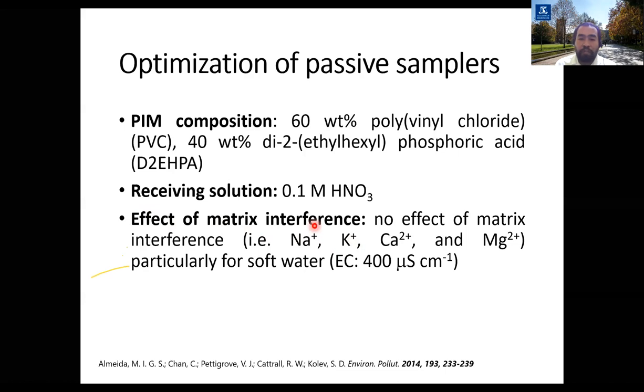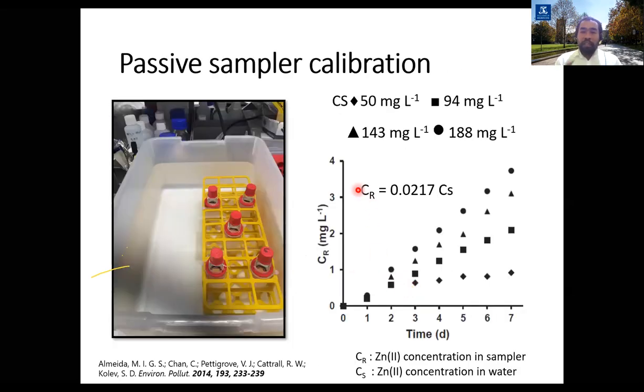They have also studied the effect of matrix interference, where they found no effect. It is commonly found in environmental water that sodium, potassium, calcium, and magnesium are the most commonly encountered cations. And because the mechanism of the accumulation of zinc is cationic exchange, these cations are expected to interfere. This is why they were selected in the study of interfering matrix. What they found is no effect of interfering matrix, particularly for soft water with electrical conductivity around 400 microsiemens per centimeter.